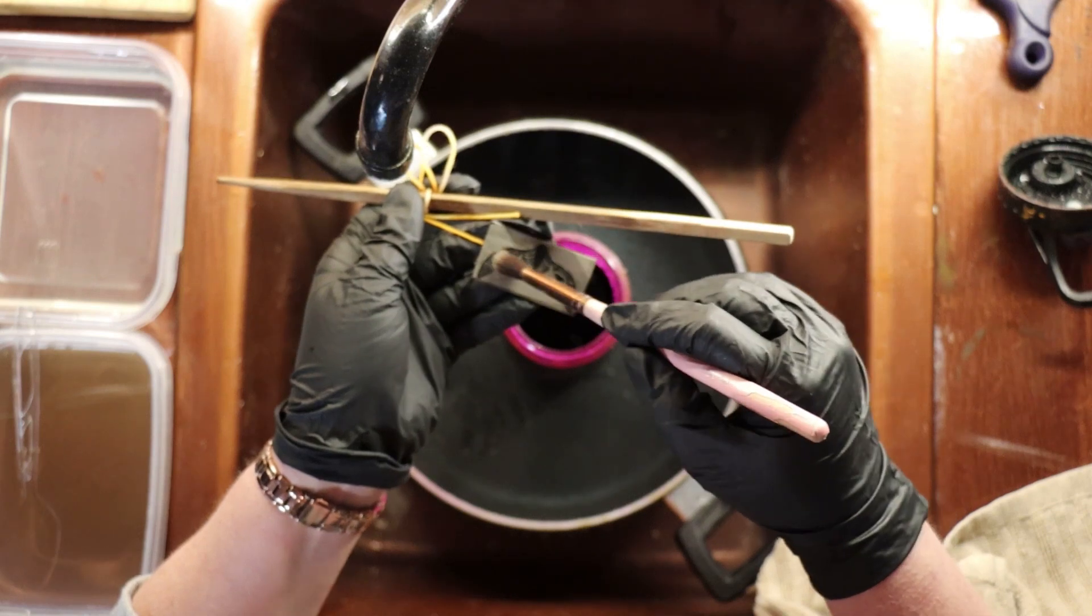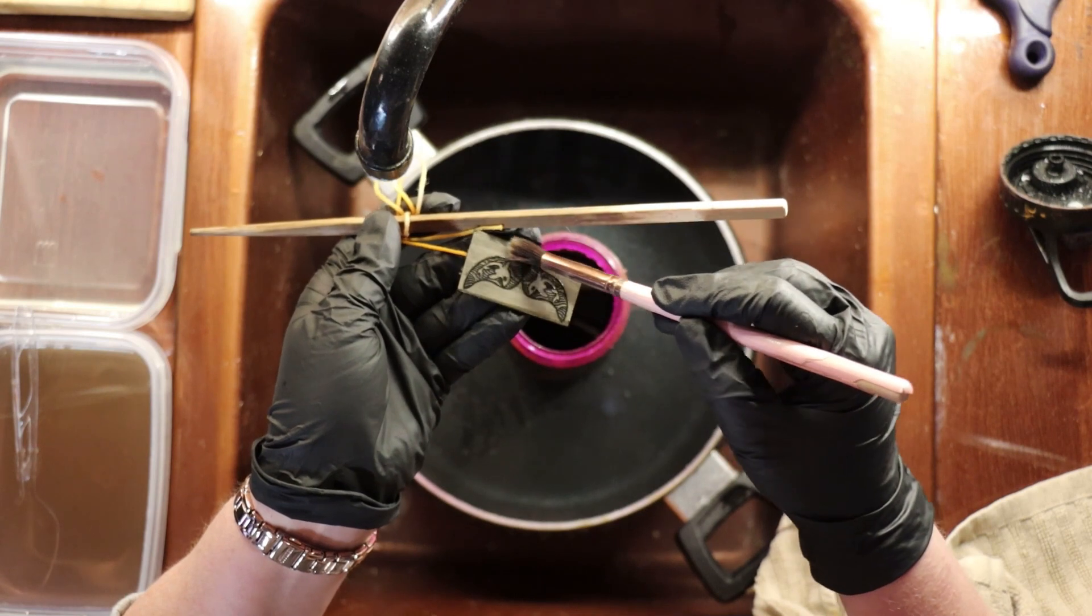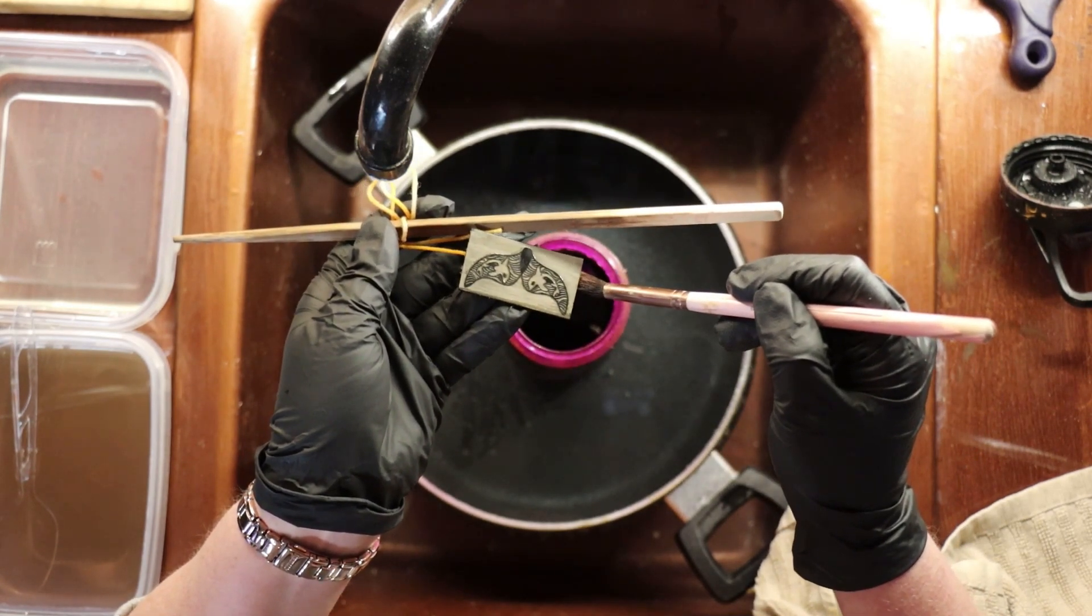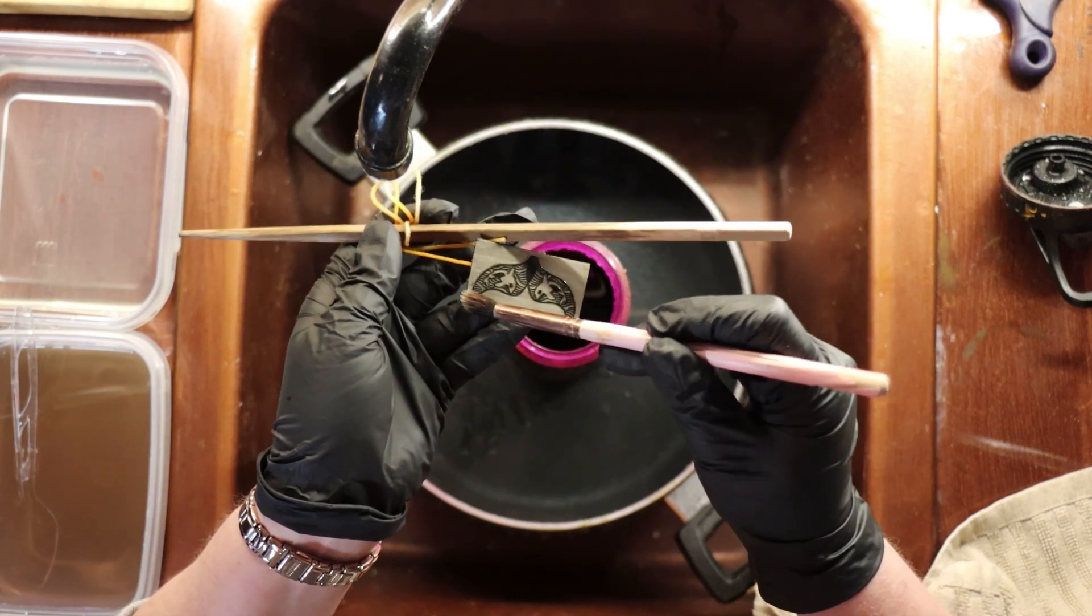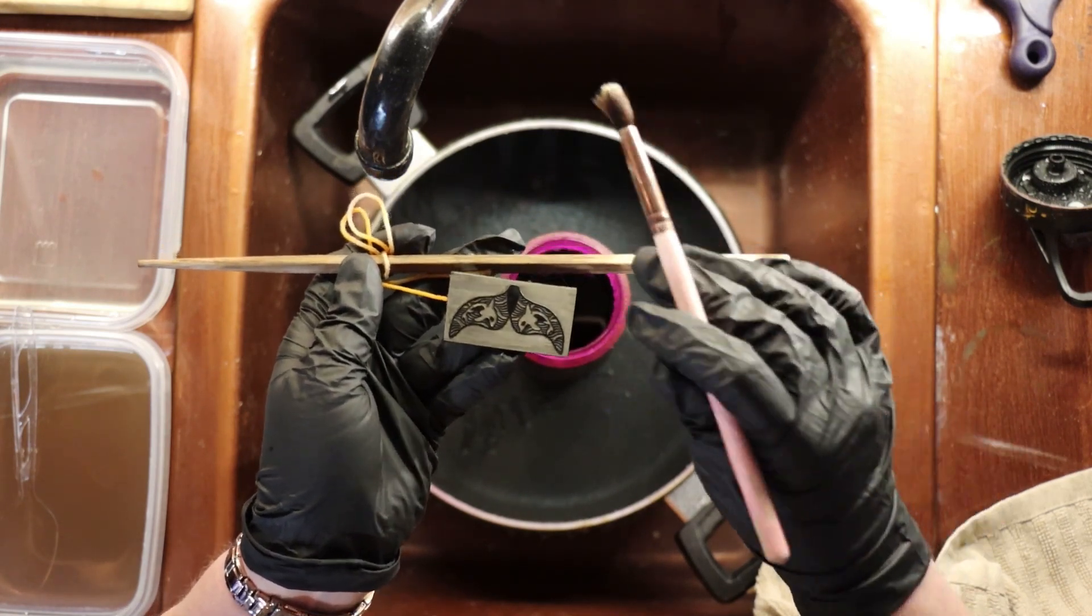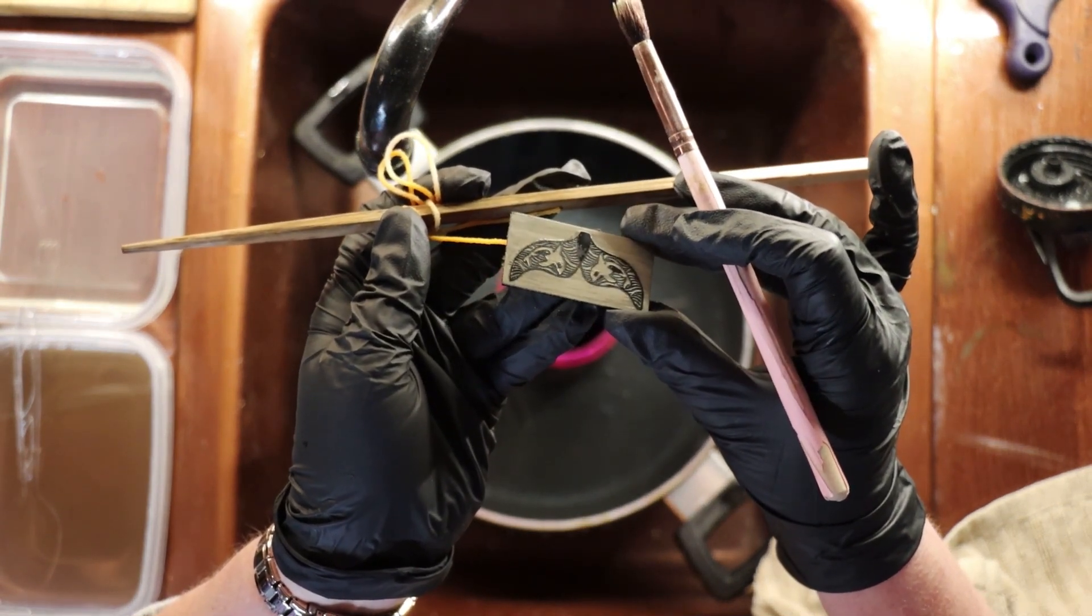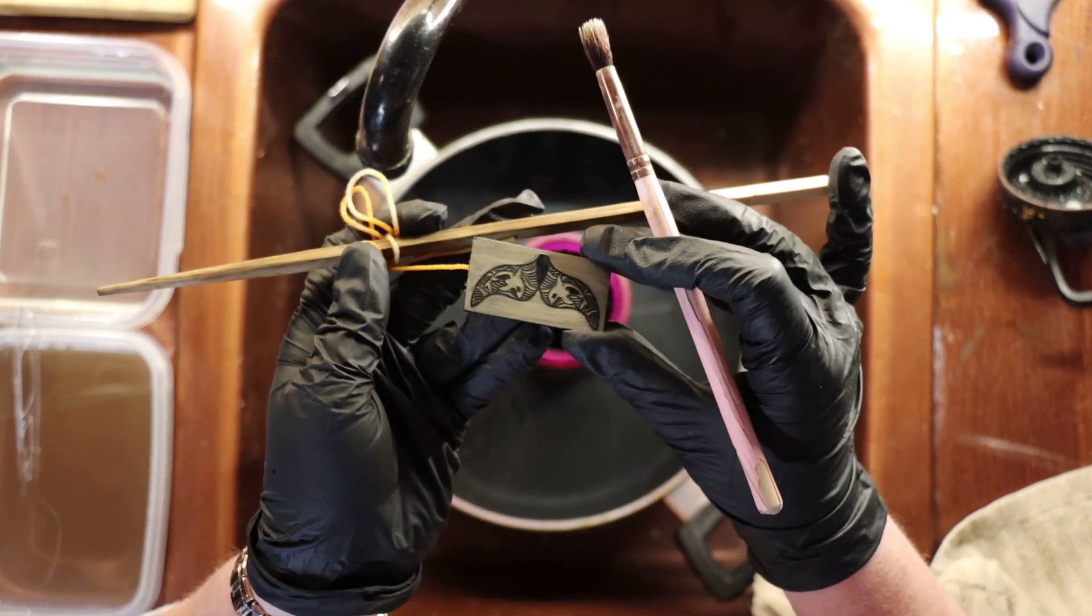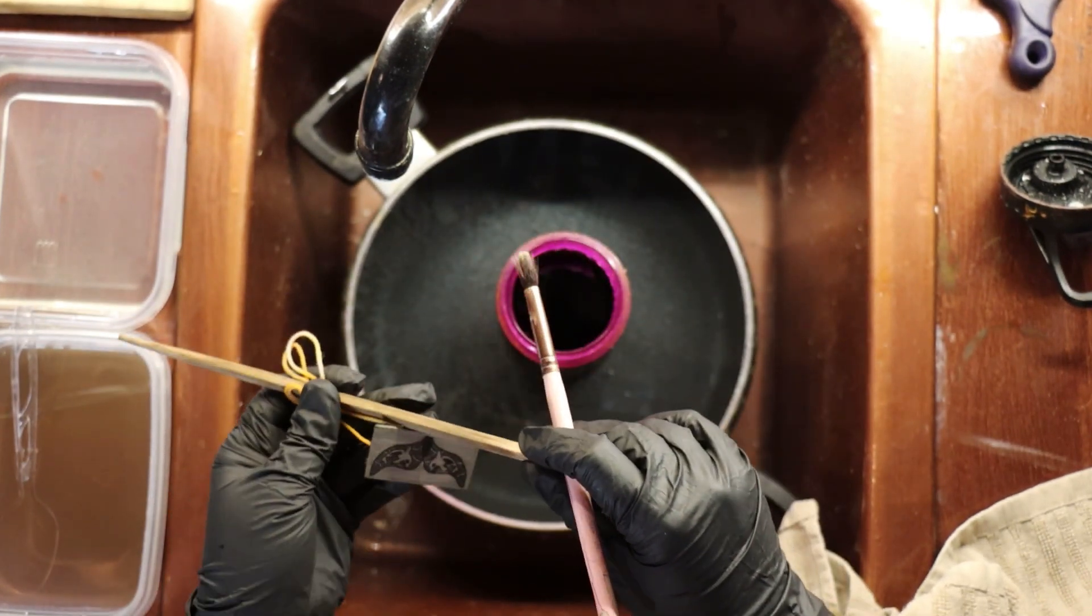Our toner held up through all of those etchings. I've tried to extend the etch another five to ten minutes, and every time that I do, the toner will bubble up at that point. So one hour is safe for me and my process, at the temperature that I keep my solution and the strength that I have it. It does quite well, and you can see that the etch and how deep it is.